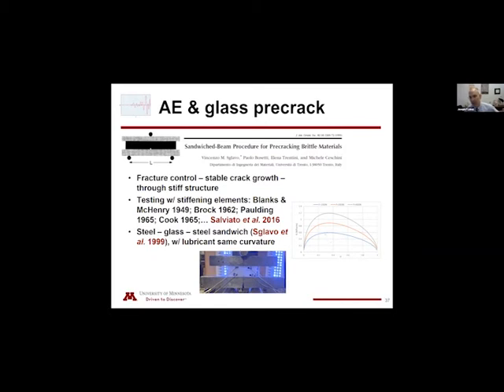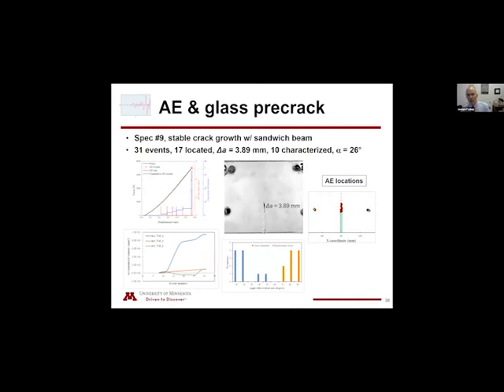I'm just indicating here what the analysis gives for this type of geometry. And if you choose a notch length appropriately, you do have stable fracture that takes place. So we were successful in stable fracture. This is the force displacement response. You see the growth of the crack, and you see locations of acoustic emission.